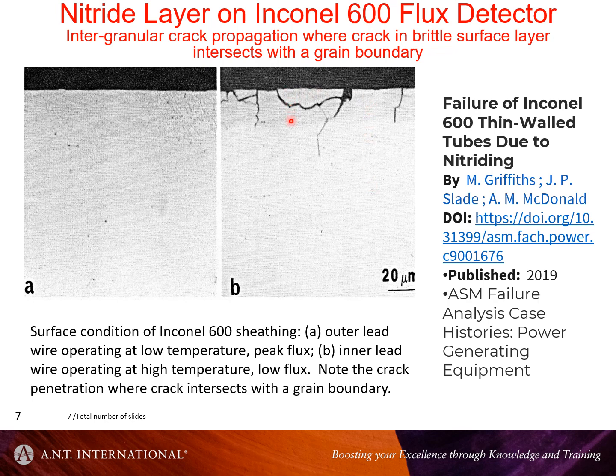And being naive and young, I said, well, okay, it's brittle where you have nitrogen layers. So we wrote a paper to do with the embrittlement due to nitriding. The idea was that the brittle layer would crack easily because it can't deform, and you've got this high stress if you bend the thing, the outer fiber stress in this layer, and if the crack intersects with a grain boundary, it will then progress further. Again, this was a bit of a naivety, but I didn't have much money to proceed further and do an in-depth study. Certainly didn't have the facilities to look into this in more detail, although I wanted to, but nobody was interested.